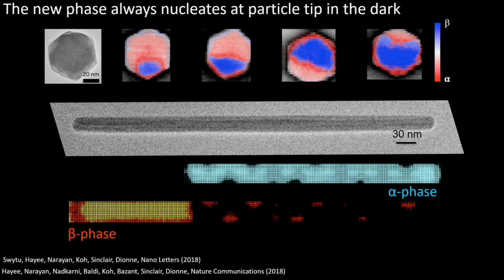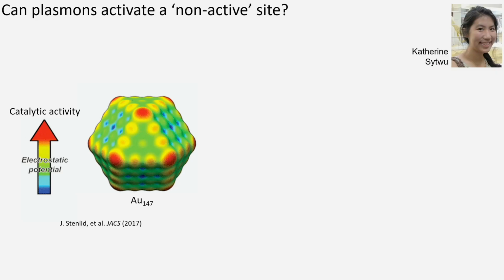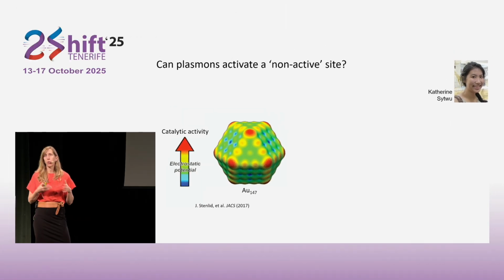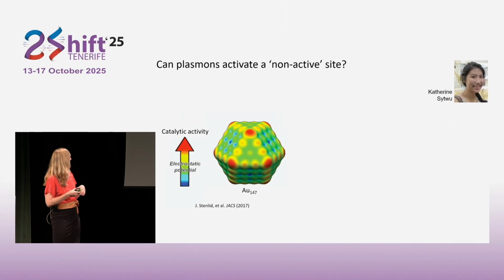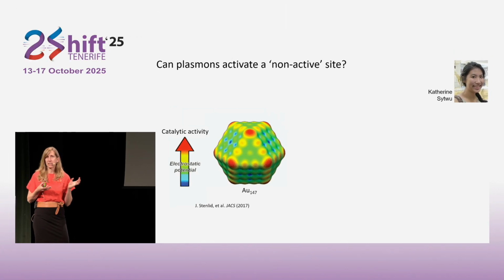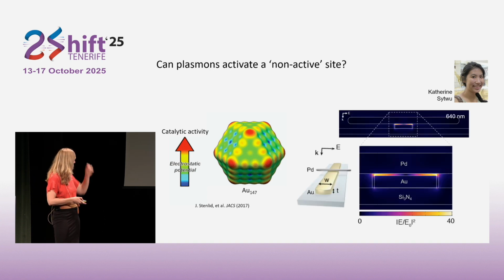Regardless of the conditions, we always have the hydrogen splitting and intercalating into these nanoparticles at the cube corners. So a few years ago, we wanted to know, okay, what happens when we start to turn the lights on? Might we have the ability to control where the hydrogen is intercalating? And can plasmons, those collective oscillations of electrons, actually activate a non-active site? So perhaps we can move away from some of those low coordination number sites.